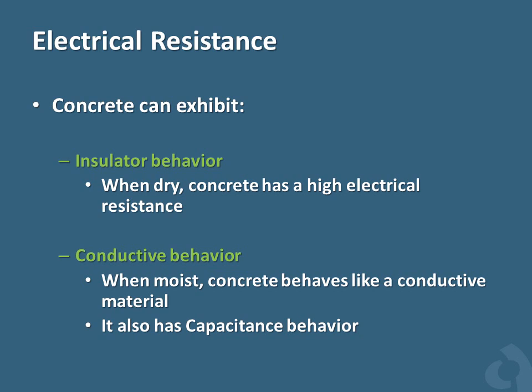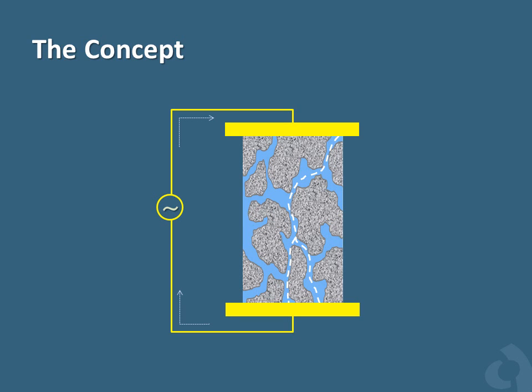This makes it difficult to measure the resistance of concrete. When concrete is subject to an electric field, the ions start to move in the pores of concrete. The ability of concrete to withstand the transfer of ions is what we call the real resistance of concrete. In this context, resistivity measurement can be used to assess the size and extent of the interconnectivity between pores. In addition, there is a capacitance property of concrete that tends to store electrical charge, and we should always consider this effect in our calculations.